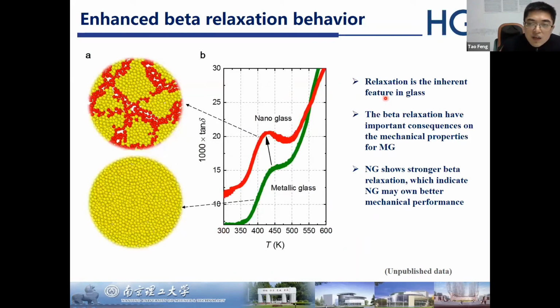And also this dynamic relaxation is an inherent feature in glass because glass is a metastable material. And the beta relaxation is especially important because it is closely related to the mechanical properties of the metallic glass. And the nanoglass shows stronger beta relaxation, which indicates the nanoglass may have better mechanical performance than the metallic glass.